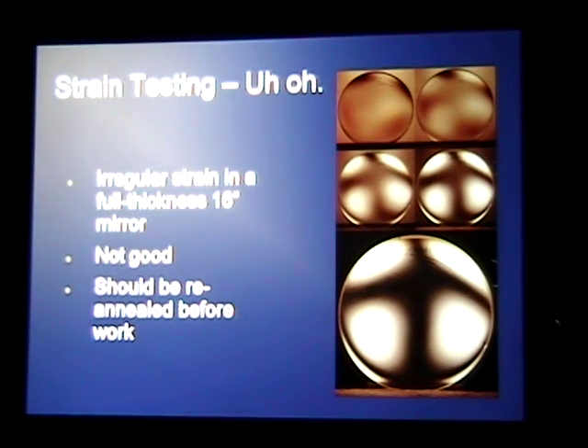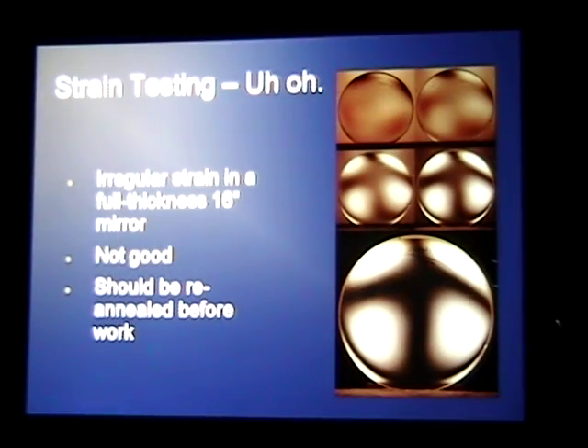Now we have some quite bad mirrors. This is rotating the polarizer. We call it the cross polarizer test because we have one going this way and one going this way. But just to show how bad this mirror was, I put them the same direction. So this is just one direction of polarized light going through the mirror. And when you see that without turning the other polarizer, you've got to say, oh no, here we go. And rotated 45 degrees or so, we see this, and at 90 degrees, we see that. And that is not something that you want to work on. It will produce probably an astigmatic mirror, and it will do weird things over the course of the night. It would definitely want to be re-annealed.